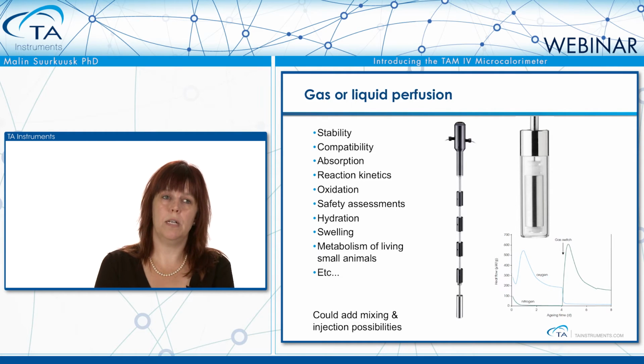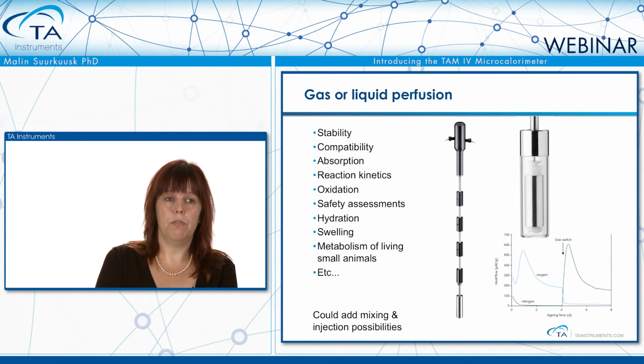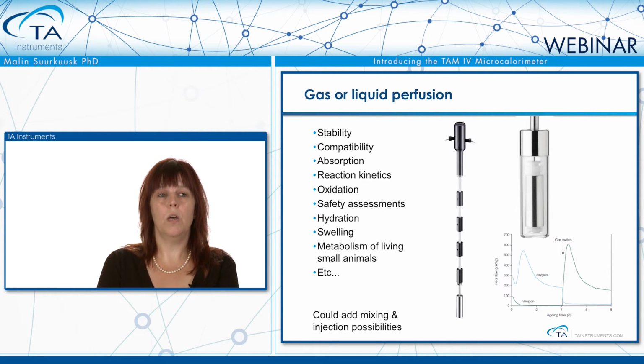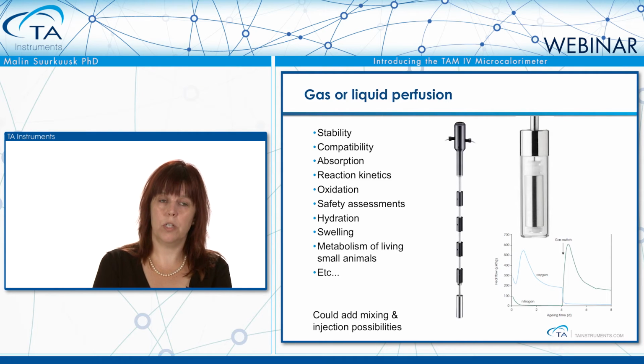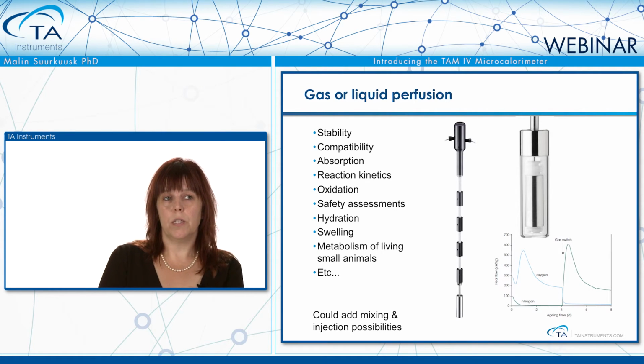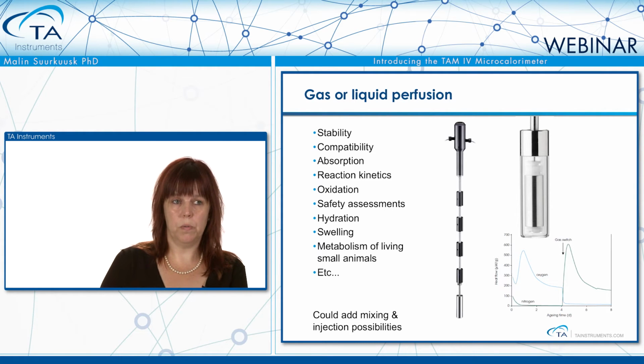It's a polymer that's put in a perfusion ampule under two different atmospheres. The blue line is the oxygen atmosphere, and the green one is the nitrogen, for the first 4 days under study. We can see on the oxygen there is a big reaction, and on the nitrogen, after the initial disturbance, the signal is at 0, so there is no reaction going on. After 4 days, gases are switched between the two channels, so the sample that was under oxygen is now under nitrogen, and we can see the reaction going back to 0 immediately. The nitrogen sample now has oxygen after the switch, and we can see that we're actually turning the oxidation reaction on by adding this gas. So this is one way of using the gas perfusion ampule.